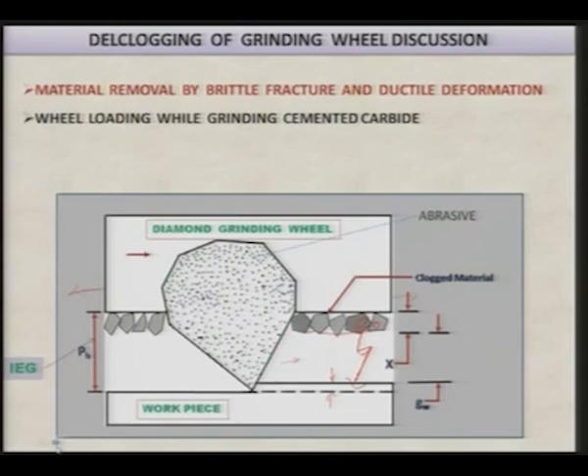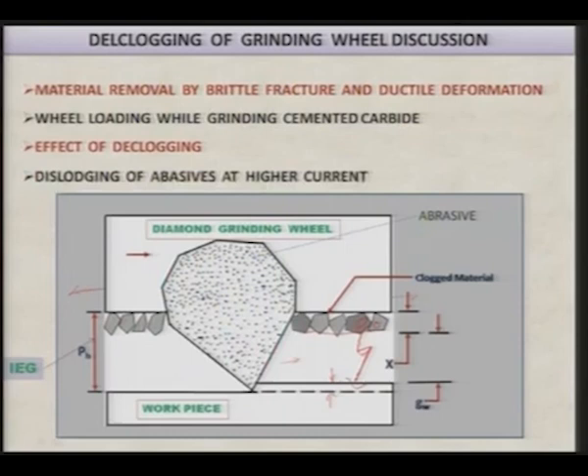Wheel loading while grinding cemented carbide has been demonstrated here with the help of a schematic model, and the effect of declogging is dislodging of abrasive at a higher current. As the clogged material gets dislodged, continuous removal of the material from the grinding wheel also keeps taking place, and the abrasive particles become loosely held by the bonding material. Due to the force acting in this direction as well as the normal force acting here, they get pulled out of the grinding wheel, and continuously fresh abrasive particles project on the grinding wheel and remove the material more efficiently than worn out material continuously removing the material from the workpiece.